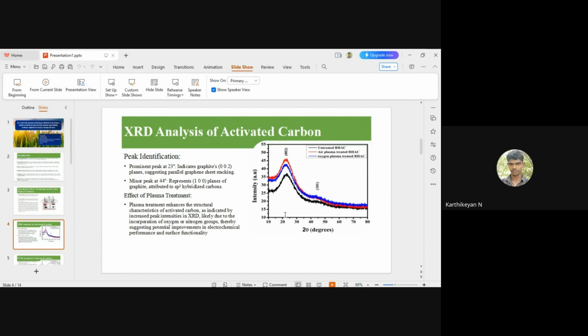The minor peak at 44 degrees represents the 100 planes of graphite, attributed to sp2 hybridized carbons. The effect of plasma treatment: the plasma treatment enhanced the structural characteristics of activated carbon, as indicated by increased peak intensity in XRD, likely due to incorporation of oxygen and nitrogen groups, thereby suggesting potential improvement in electrochemical performance and surface functionality.